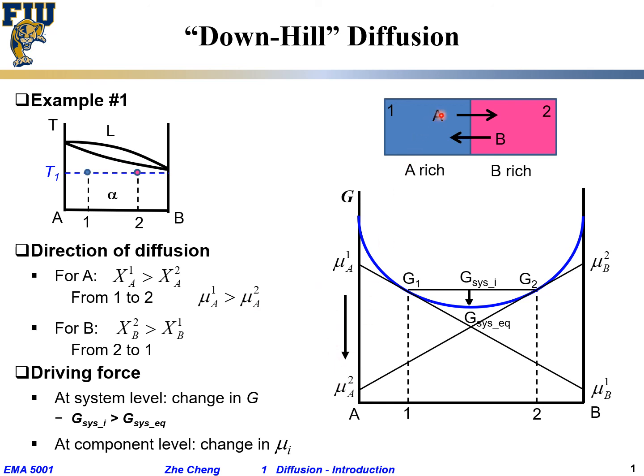For element B, piece two initially has higher chemical potential: mu_B2 is higher than mu_B1. As a result, element B flows from high chemical potential to low chemical potential — from piece two to piece one. In summary, this process is driven at the system level by reduction in Gibbs free energy, and at the component level by reduction in chemical potential for each species.